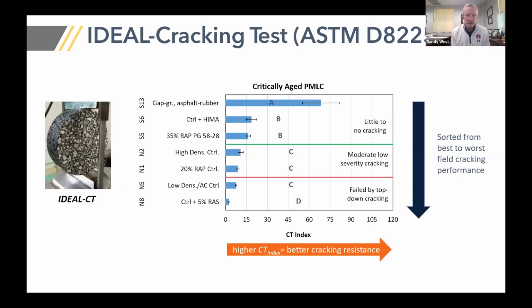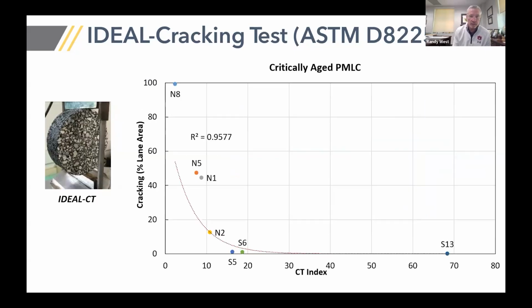The IDEAL-CT is the most popular test being used around the country for BMD. It also did a very nice job of correlating with the field performance in this experiment. Good statistical groupings, and the XY correlation very strong, R squared of 0.96. So a really strong correlation between lab and field results.